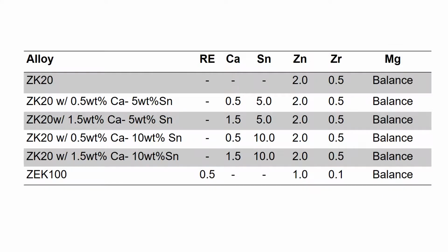The magnesium alloys that we studied had 2 weight percent zinc, 0.5 weight percent zirconium, and varying weight percentages of calcium and tin. The weight percent of calcium varies from 0.5% to 1.5%, and for tin it ranges from 5 to 10%. The ZEK100 alloy has 0.5 weight percent of REs, 1 weight percent of zinc, and 0.1 weight percent of zirconium. Another factor that was taken into consideration is how the heat treatment, cold work, and a combination of both affected the mechanical properties of the alloys.